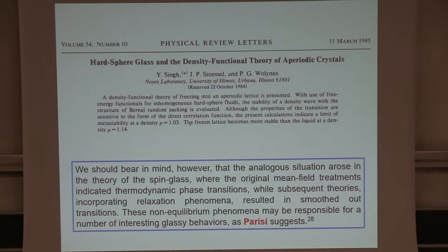What we found was that if you took a specific amorphous structure, heated it up above a certain level or lowered its density, it would fall apart at some point. There was a limit of stability that occurred at a density rather close to the densities people found in simulations of those early days, short simulations of what people were then calling a glass transition.